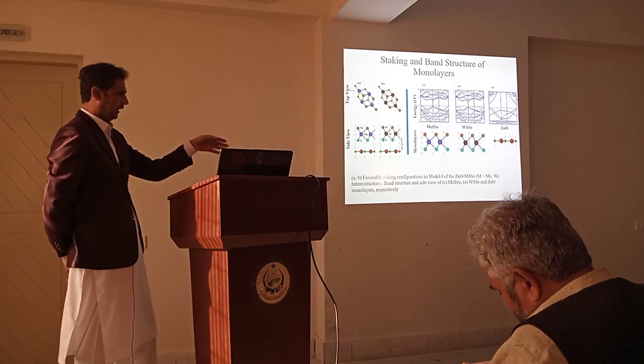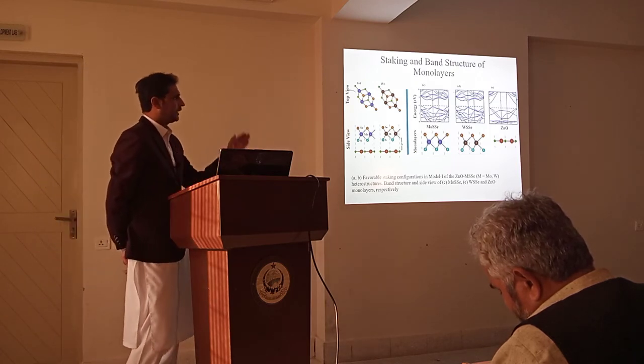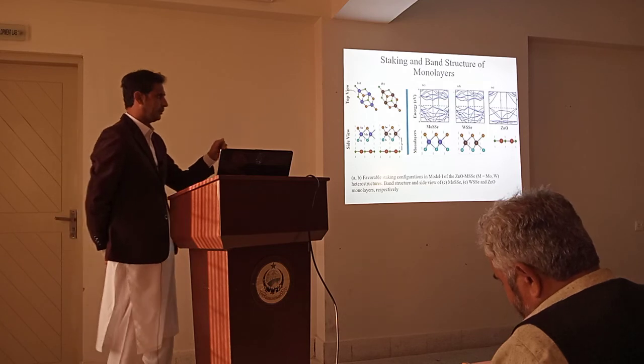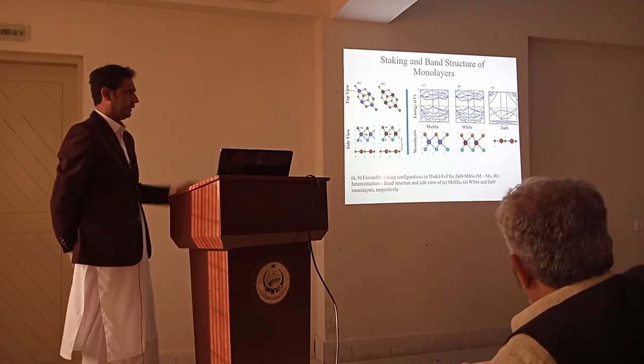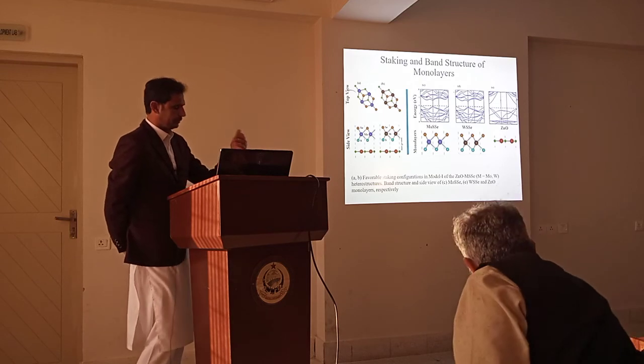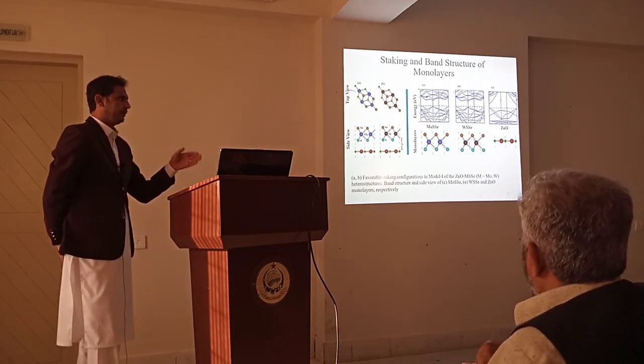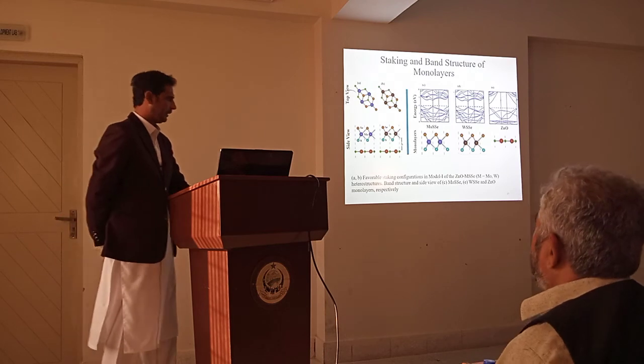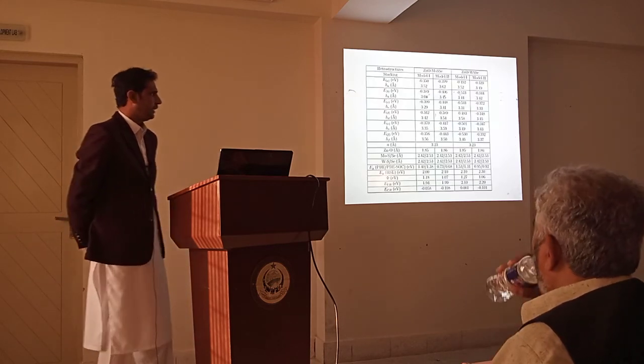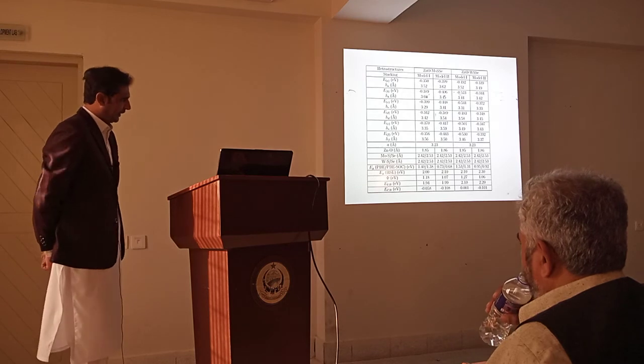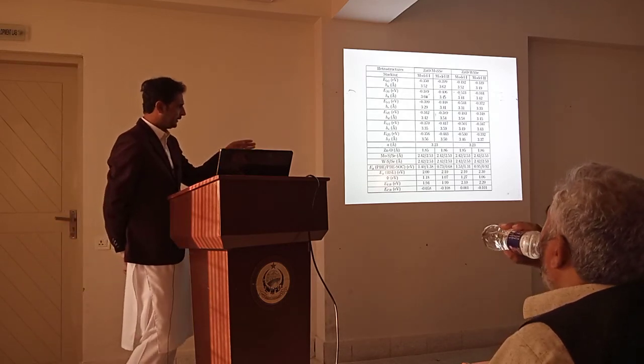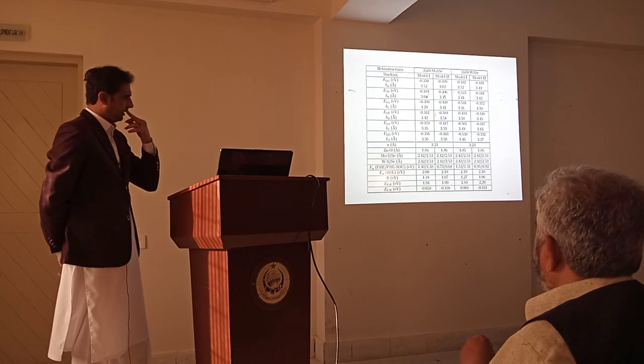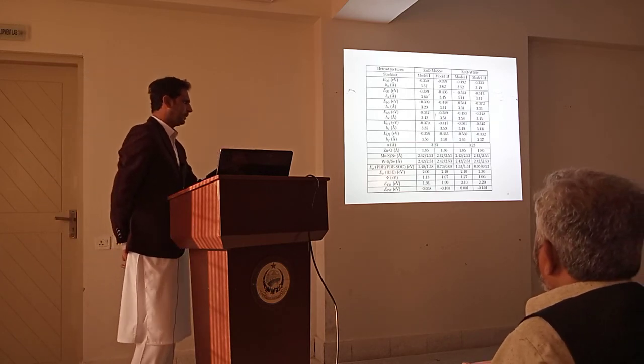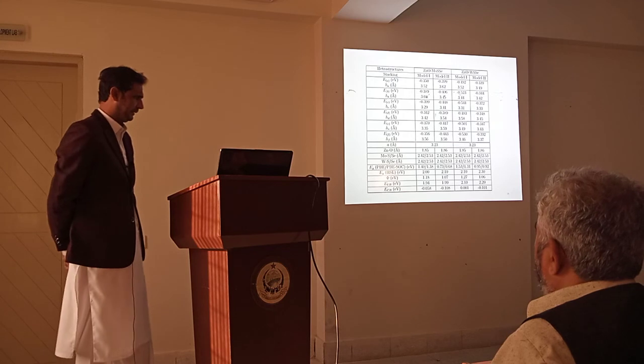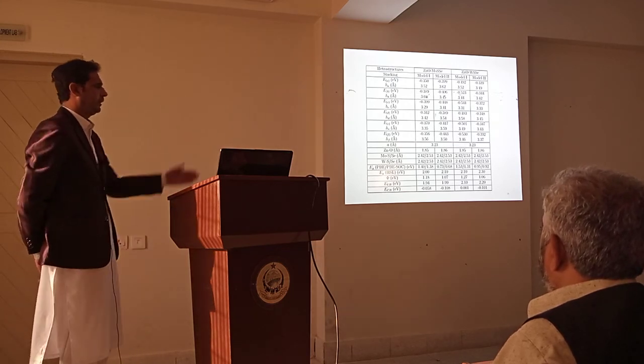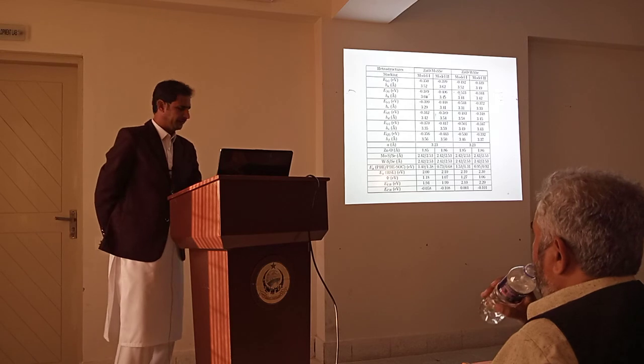As I discussed in my first paper, MoSSe and WSSe are direct band gap, where the VBM and CBM lie at the K point. In the case of ZnO, it is also direct band gap, where the CBM and VBM lie at the gamma point of the first Brillouin zone. These are the calculated values of interlayer distance, binding energy, lattice constant, bond length, and band gap using PBE plus SOC, also HSE. This is the work function, and these are the values for water splitting.